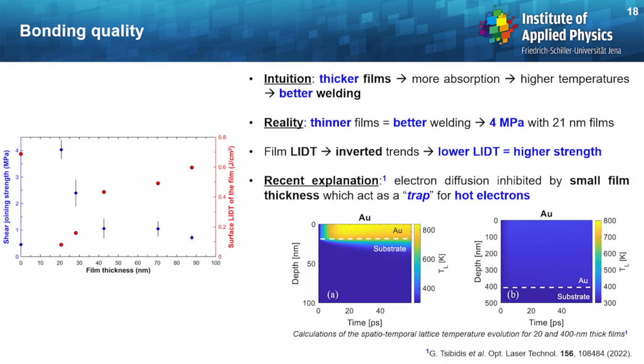And this was recently explained theoretically by electron diffusion, which is in this case inhibited by the small film thickness, which then acts as a trap for the hot electrons. As you can see here on these figures, for a 20 nanometer film, you may reach 800 Kelvin, while for a 400 nanometer thick film, you barely reach 300 to 400 Kelvin.